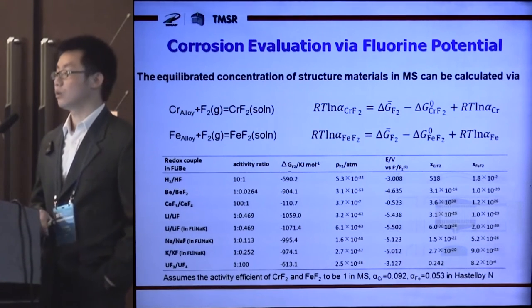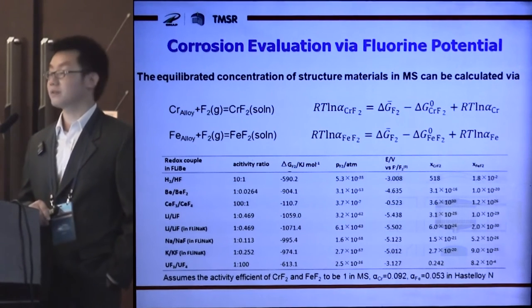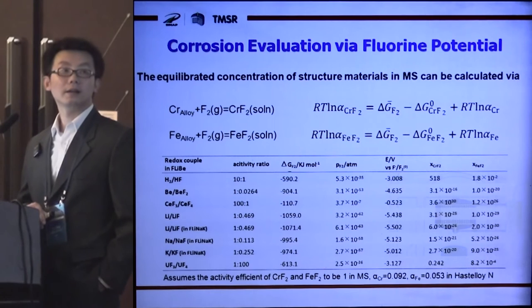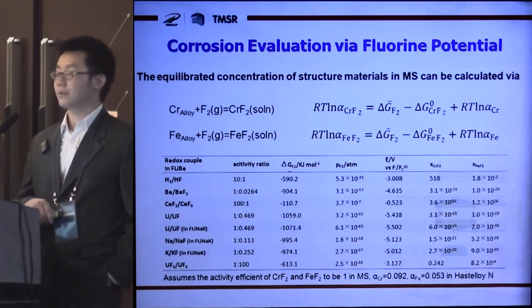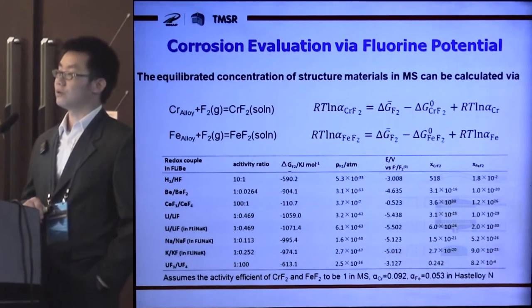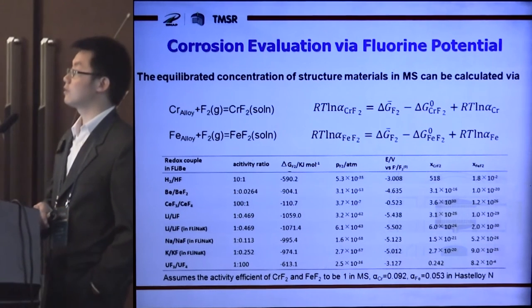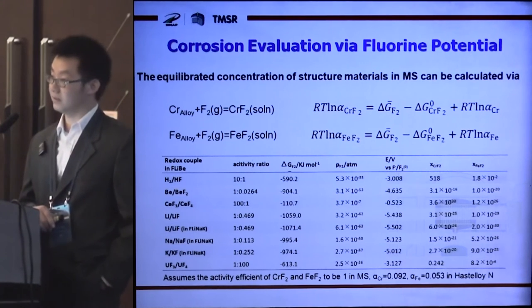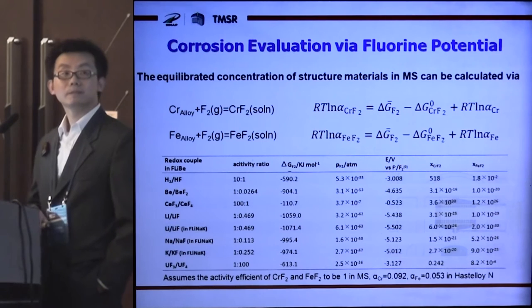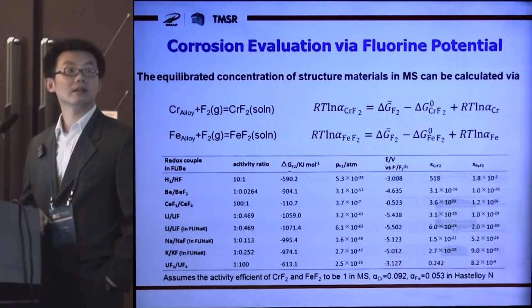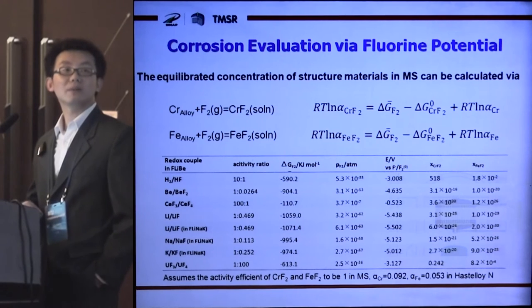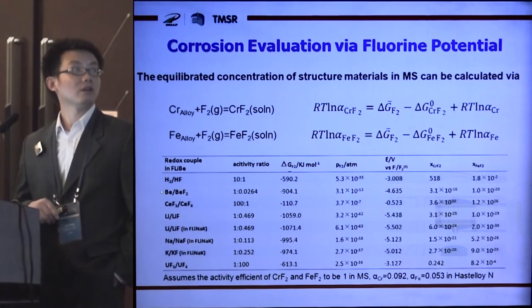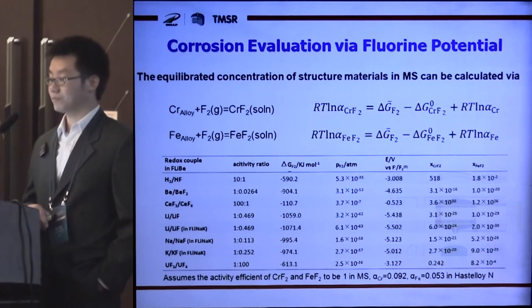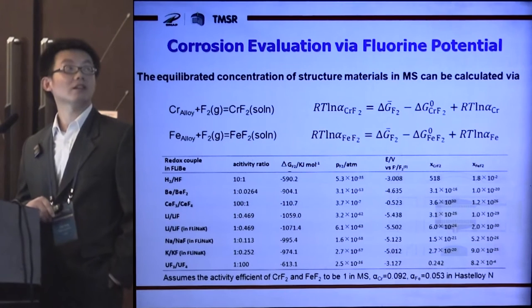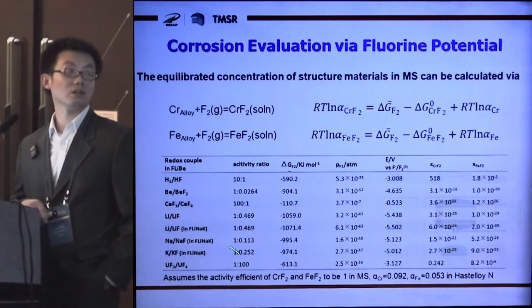From these results, we can choose a suitable redox couple to control the corrosion. For example, the UF3 and UF4 redox couple was chosen to control the redox potential in MSRE and obtain satisfactory results. From these calculations, we can also say the alloy may be well protected by these metal containing redox couples. However, some other characters of the metal containing redox couples should be considered before we draw this conclusion.